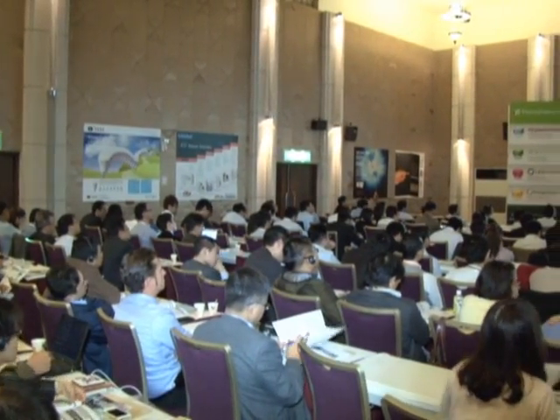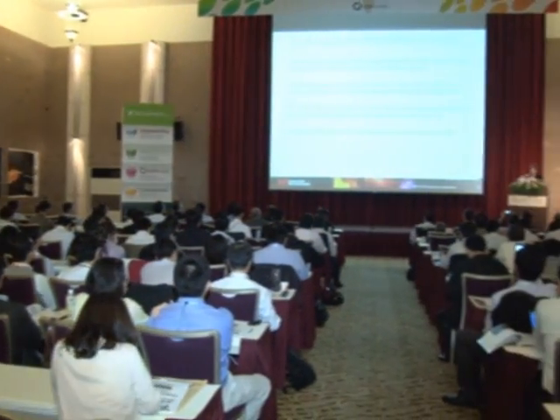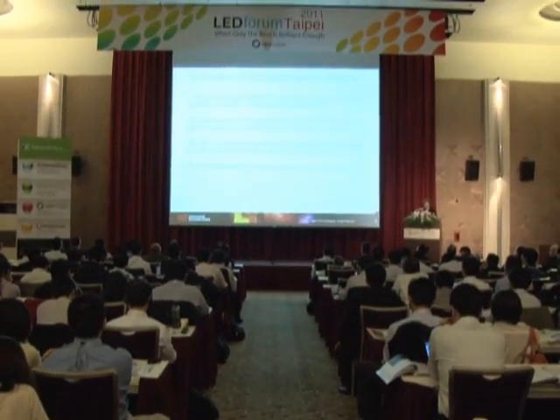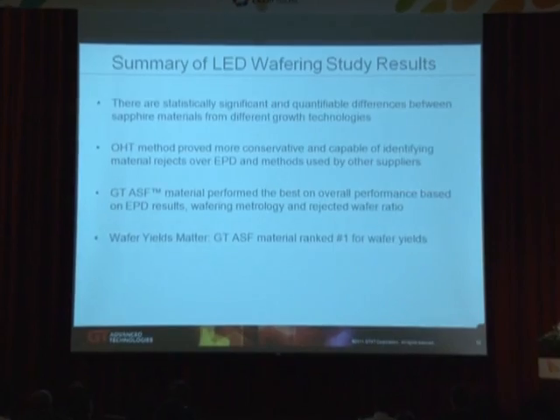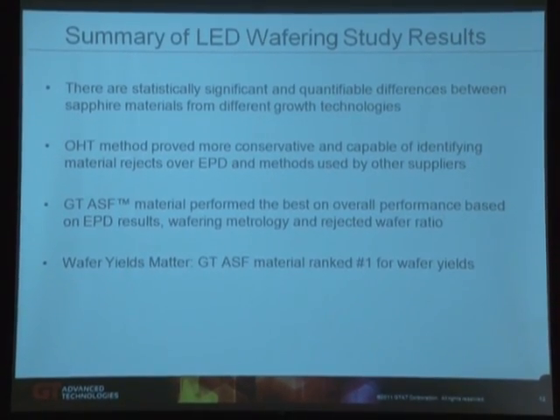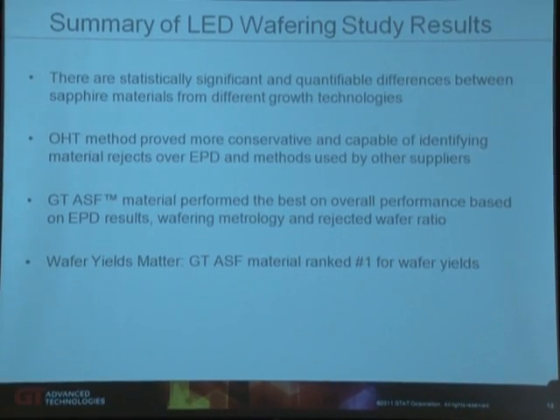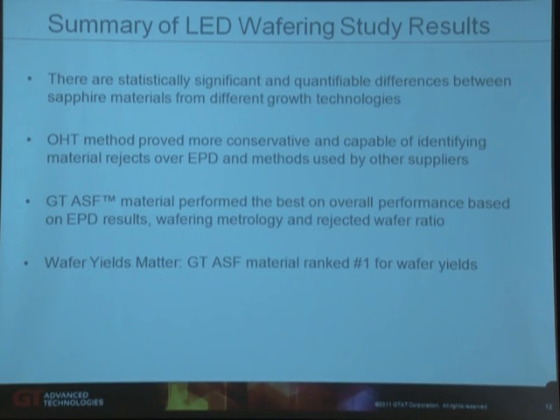So in summary, these are statistically significant and quantifiable differences between sapphire materials with different growth technologies. The OHT method proved more conservative and capable of identifying material rejects over EPD and method used by other suppliers at the core and boule level, meaning the material was identified as LED grade or non-LED grade before it went into the wafering process and before the wafering house spent money processing the material. GT ASF material performed the best on overall performance based on the EPD results, the wafering metrology, and the rejected wafer ratio. Wafer yields matter, and GT ASF material ranked number 1 for wafer yields.